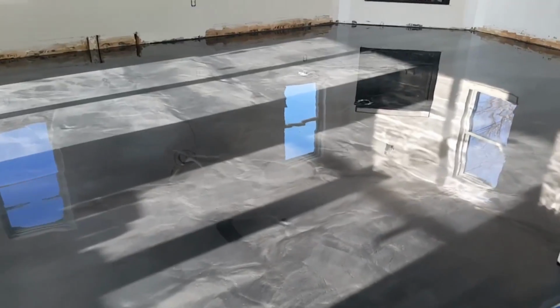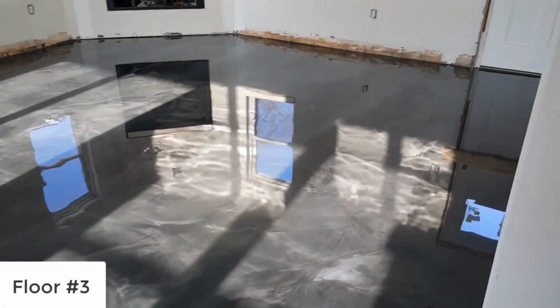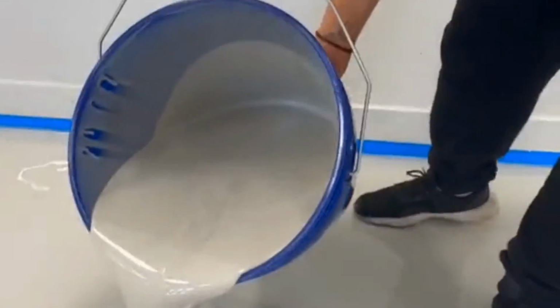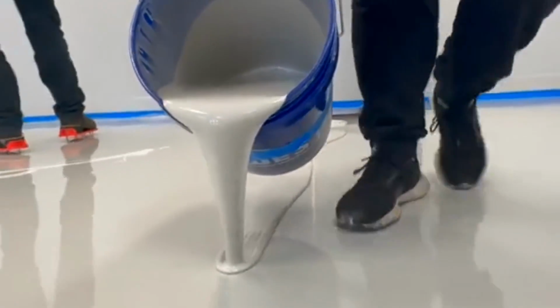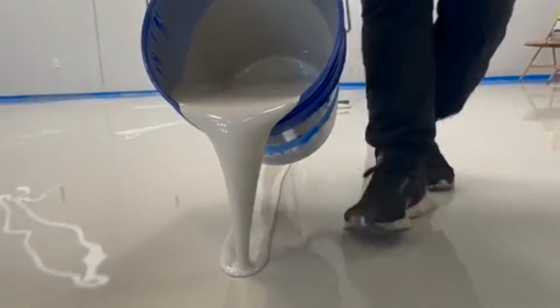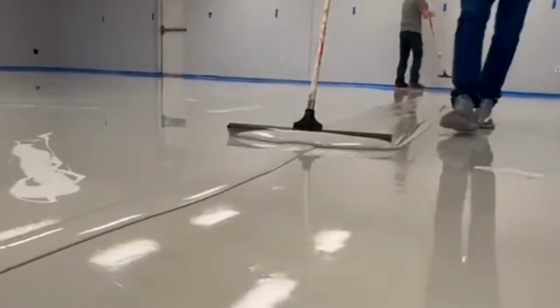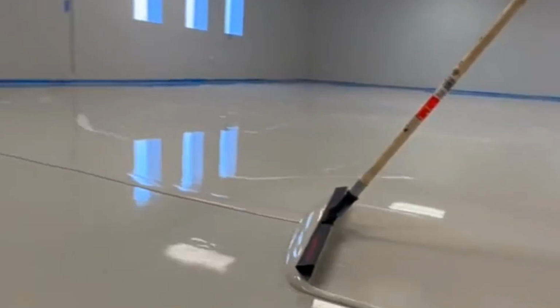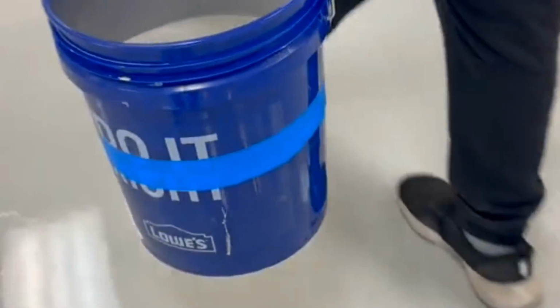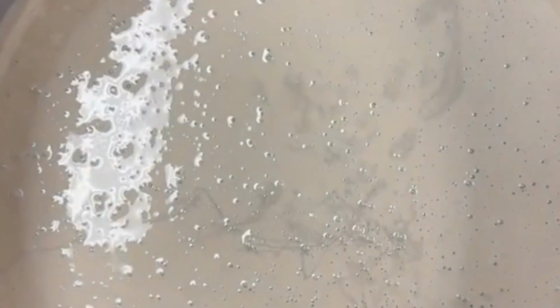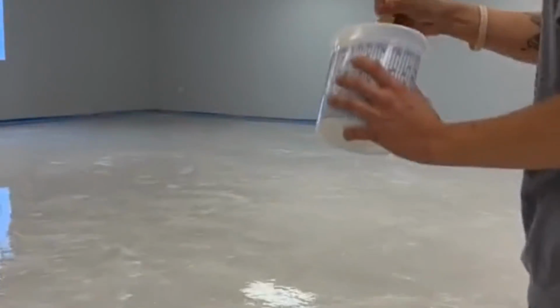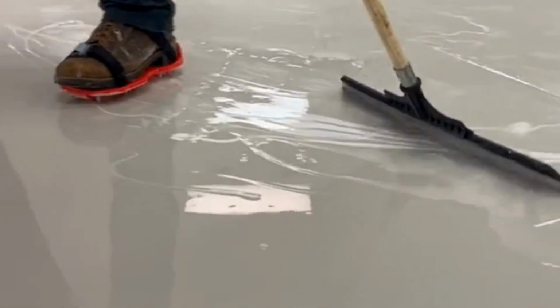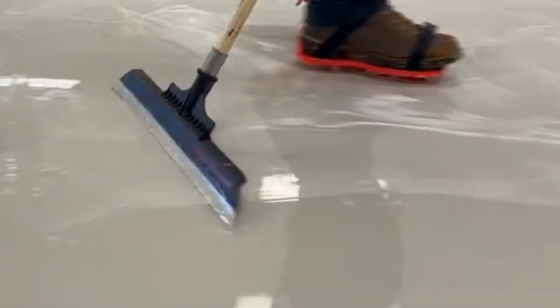Step 3. Applying the final epoxy coat. This layer will provide the ultimate durability and shine. Application process. 1. Pour epoxy in an S or zigzag pattern. 2. Spread evenly with a notched squeegee. Maintains thickness. 3. Backroll with a lint-free epoxy roller for a smooth finish. 4. Use a heat torch or spiked roller to remove air bubbles. Warning: work fast. Epoxy begins curing within 30 to 40 minutes.